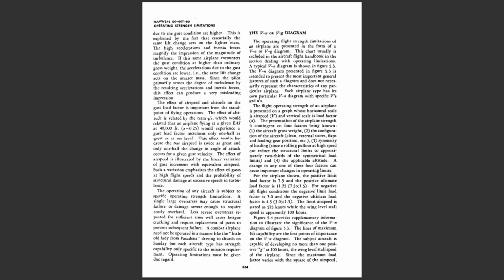The effect of airspeed and altitude on the gust load factor is important from the standpoint of flying operations. The effect of altitude is related by the term square root lowercase sigma, which relates that an airplane flying at a given EAS at 40,000 feet, where lowercase sigma equals 0.25, would experience a gust load factor increment only 1/2 as great as at sea level. This effect results because the true airspeed is twice as great, and only 1/2 the change in angle of attack occurs for a given gust velocity.